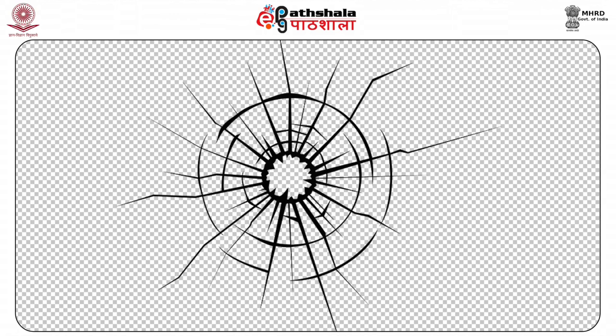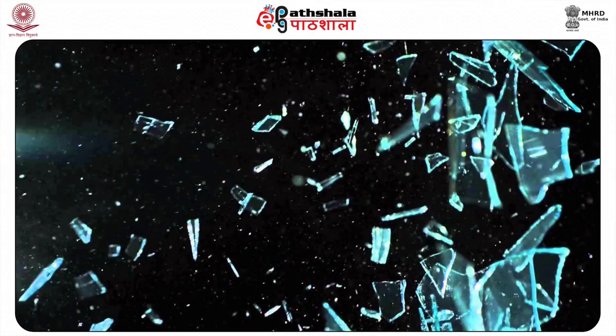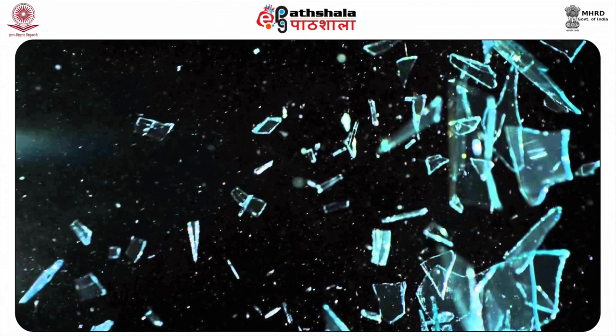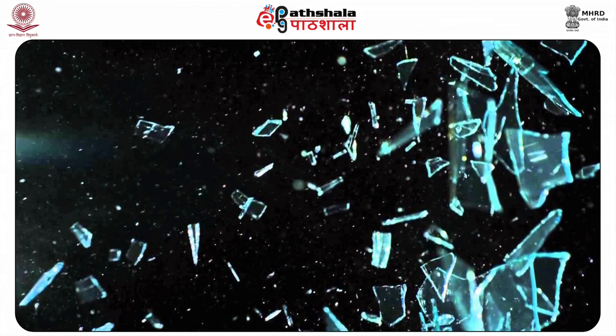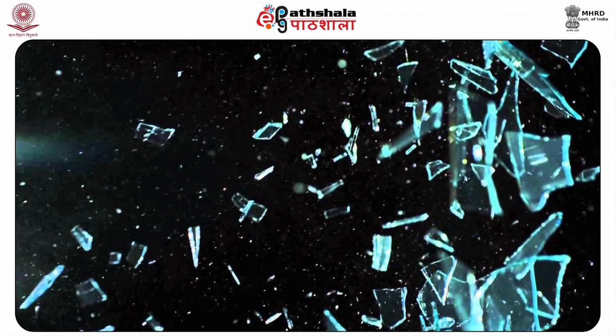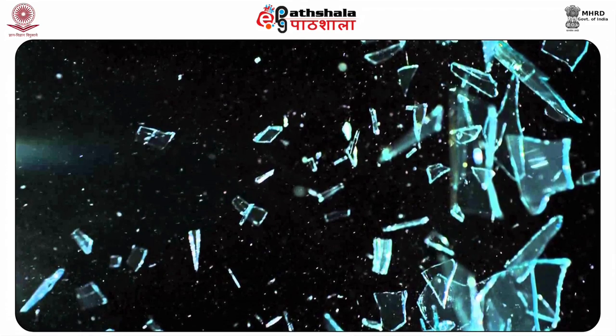Easily deformed or low velocity bullets such as 0.32 S&W and 0.38 S&W will generally have insufficient velocity to penetrate laminated windscreen or bank teller glass, giving up all their energy on impact. As a result of the transfer of energy, the glass around the impact site, on both the contact and remote glass laminates, will be crushed. Glass will be thrown off the rear face from the remote side of the glass with considerable force. Crushed glass will also be projected some distance back from the contact site towards the firer.